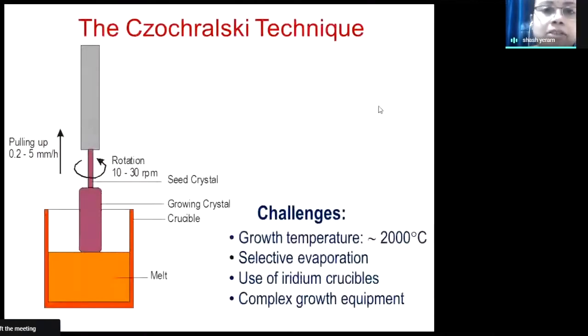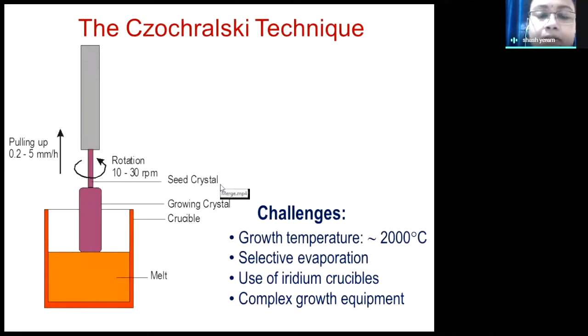So this is the Czochralski crystal growth technique. Here the material is kept in a crucible and then it is melted. The melting is at a very high temperature, as I said. And for this crucible, normal materials cannot be used. So you have to use very high melting point metals, which are not reacting with the melt. So this is either an iridium crucible, or sometimes people use molybdenum or tungsten, like that.